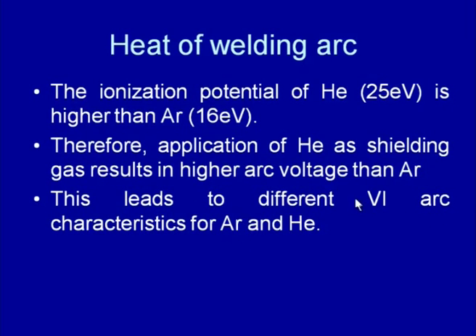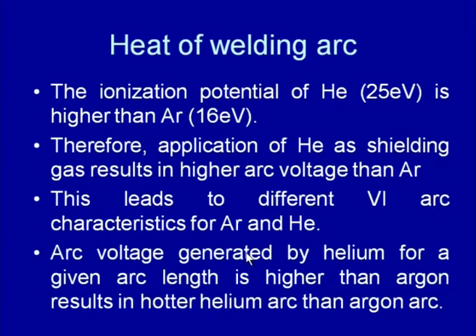So, because of the difference in the arc voltage when helium is used than argon, we get a different VI characteristic for argon and helium. And the VI characteristic for helium is always above that of argon under identical arc length conditions. So, the arc voltage generated by helium for a given arc length is found to be higher than that generated by argon, which in turn results in a hotter helium arc than the argon arc, and a hotter helium arc helps in deeper penetration and faster melting for welding of thick sheets and metals of high thermal conductivity.